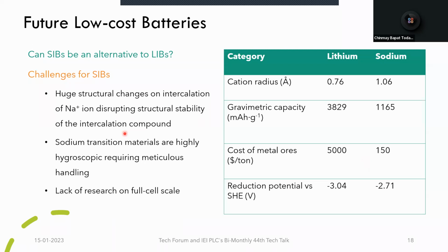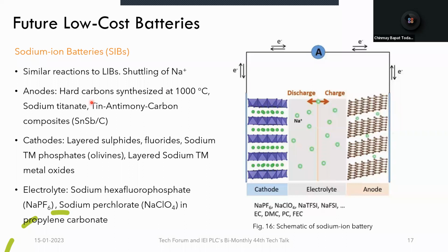So when you talk about graphite and lithium, the structural changes were around 10%, because the cation radius of lithium is 0.76 angstrom, and it is around 30% more for sodium. So we can expect around 20 to 30% structural changes if we continue to use graphite. But if we use any other material which can reversibly integrate at the anode, as I mentioned, hard carbons, because we cannot use graphite because the spaces in between the graphene layers are not sufficient to intercalate the sodium. So when we use these particular anodes, the volumetric changes are slightly higher than lithium. I do not know the exact percentage, but my guess would be around 20% at least.